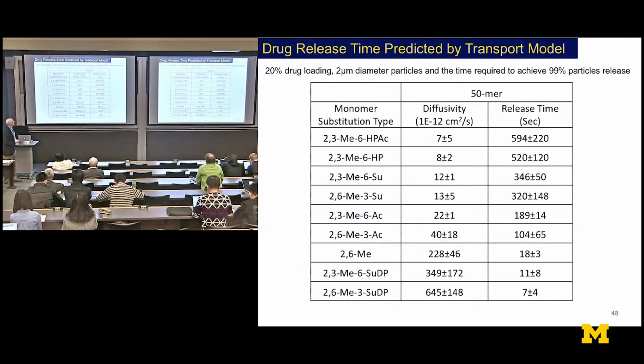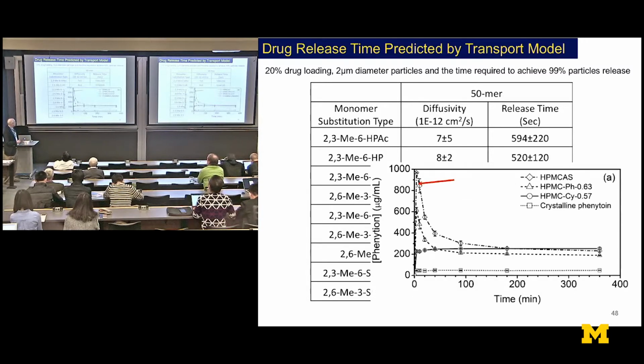This shows the diffusivity that we obtain from our simulations, as well as the release time from a particle of a given size. And you can see this very large dependence on the composition of the excipient on the release time. And these correlate reasonably well with release times that are seen from mixing solid dispersions in aqueous medium in experiments.